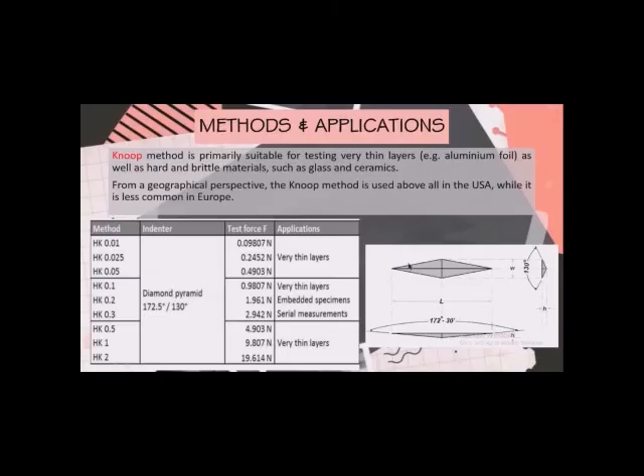Hi, this is EP. Now I want to explain about the Knoop method and applications. The Knoop indentation is rather long and narrow and less deep compared with the broader and rounder Vickers indentations. The Knoop method is primarily suitable for testing very thin layers, for example aluminum foil, as well as hard and brittle materials such as glass and ceramics. Why do brittle materials use the Knoop method? Because the Vickers method has deeper indentation than the Knoop method, it will make cracks around the edges of the materials, which can be avoided with the shallower Knoop indentation.